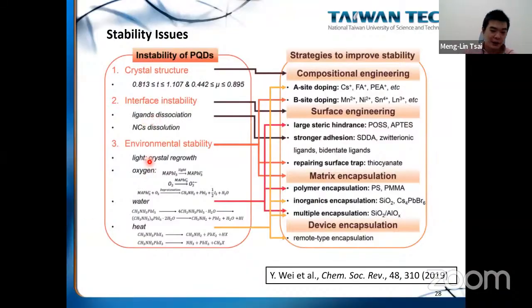There are also some environmental issues. For example, if you have oxygen or water, it will react with this type of quantum dot. So different strategies have been applied. For example, we can use compositional engineering to improve the structural instability, and we can use surface engineering. We change the ligand to control the interaction between the crystal and the ligand, to come up with a more stable nanocrystal. And we can use encapsulation techniques to further protect it